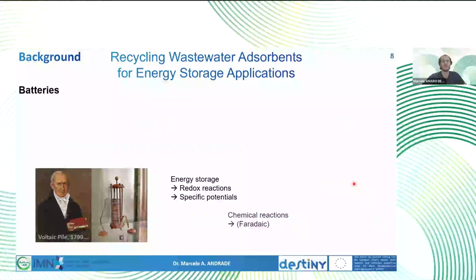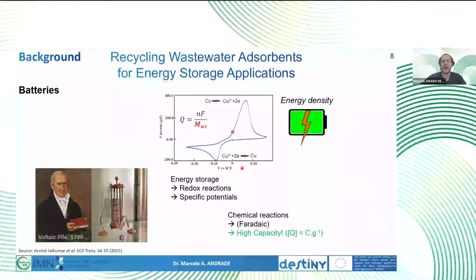These materials can provide high power, but batteries, on the other hand, rely on chemical energy or electrochemical reactions. So the reactions happen at a specific potential and they can store a lot more energy because you have active chemical species that will exchange electrons, and basically the amount of charge you can store depends on the molecular weight of these cations or molecules that will exchange electrons. So they can provide very high capacity coming from these redox reactions, but they happen relatively slower than with supercapacitors.